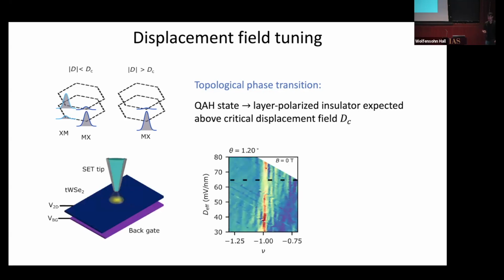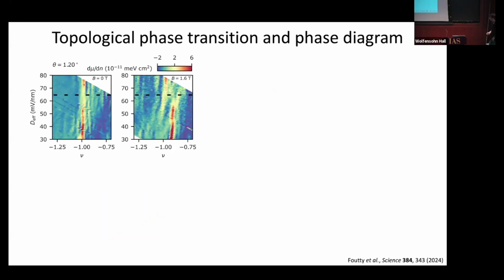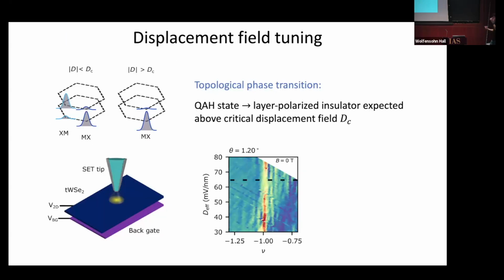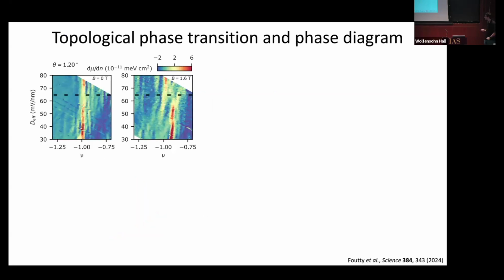And indeed, we can use our tip to apply a local electric field to the sample, just by changing basically the voltage difference between tip and sample. And so this is an example of an image of inverse compressibility as a function of effective displacement field, now that we're tuning with our tip, and filling factor. And so you can see there's some incompressible state at nu equals 1. And as you increase the displacement field more and more, it starts to weaken initially. And then at the highest displacement fields, it gets stronger again. So you might think maybe this is a sign of the theoretically predicted topological phase transition. We can explore that more.